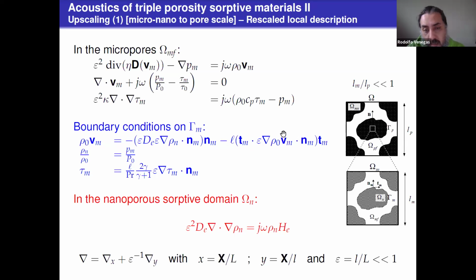One of them comes from the rarefaction effects, so the velocity is proportional to this tangential component of velocity. And then this is to do with the normal component of the velocity, which is associated with the mass flux. And this epsilon comes from the scaling, and in particular, these two epsilons account for the fact that rho n varies at the local scale, and the other epsilon comes from the fact that this mass flux is an order smaller than the mass flux generated by the acoustic waves propagating in these micropores.